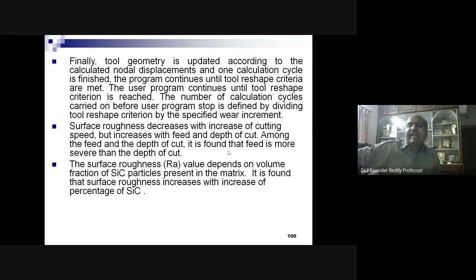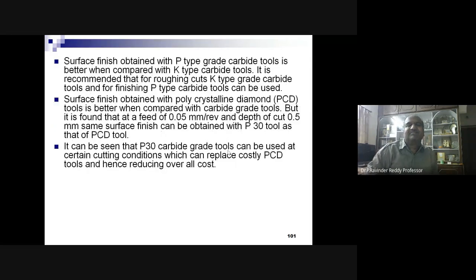The surface roughness decreases with increase of cutting speed, but increases with the feed and depth of cut. Among the feed and depth of cut, it is found that the feed is more severe than the depth of cut. The surface roughness value depends on the volume fraction of silicon carbide particulates present in the matrix. It is found that surface roughness increases with increase of percentage of silicon carbide.